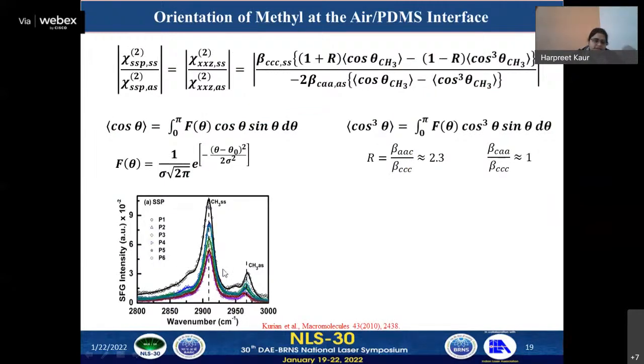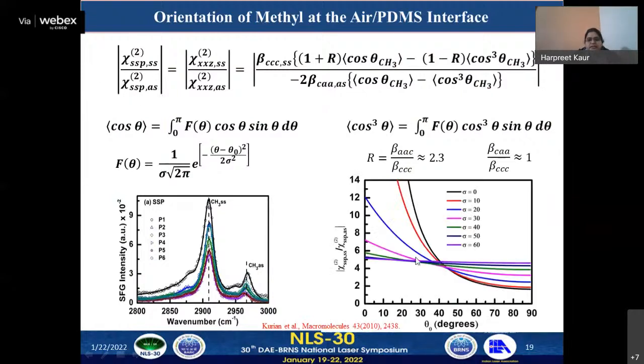And this is the SFG L-factor corrected SFG spectra. The amplitude ratios of this are used to determine this ratio, which intersects with the experimental and theoretical curves, which are determined from this expression, for various sigma values. So the intersection between these experimental values and the theoretical lines gives the value of the orientation of the methyl group at the air polymer interface.